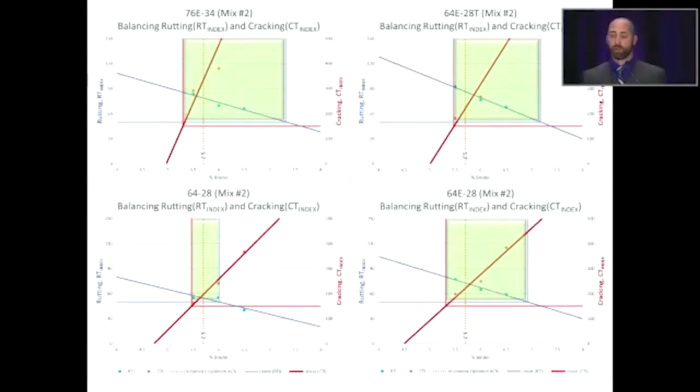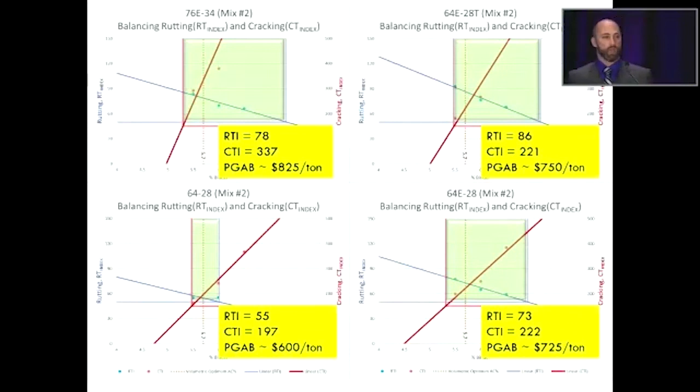But in cases where you have increased risk of rutting or increased cracking concerns, you can use a higher grade binder, but you need more of it. This is just a quick shot to give you some financial aspect, some association to the cost implications. So as you go, base 6428 at $600 a ton, you see that increase in cost as you go counterclockwise. The cost increase can be significant, but are you seeing a performance gain?